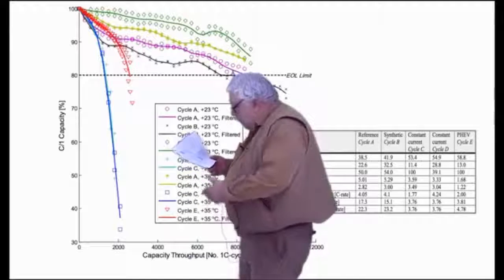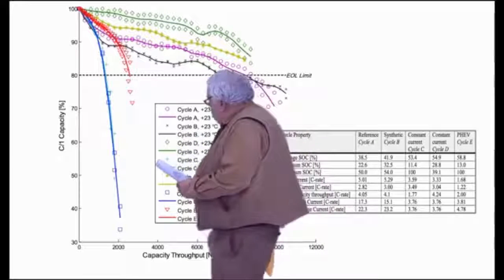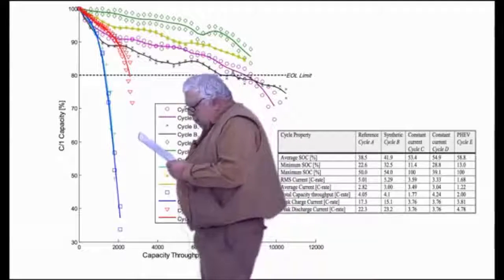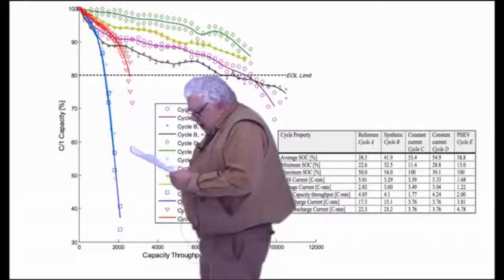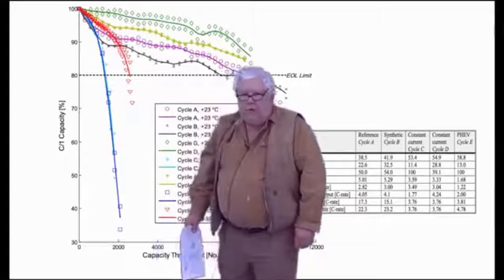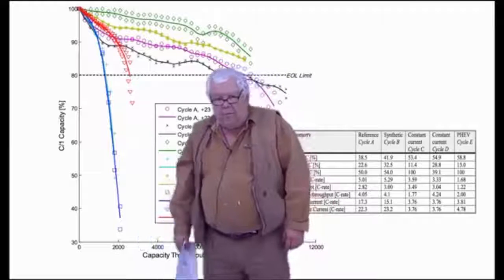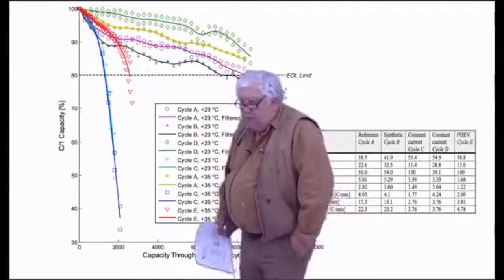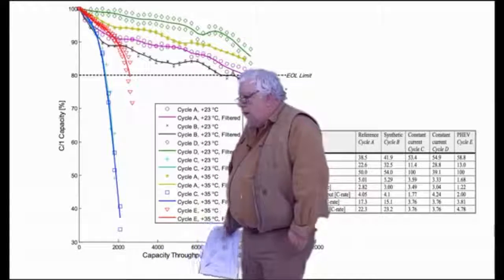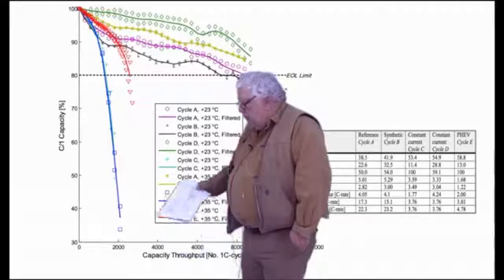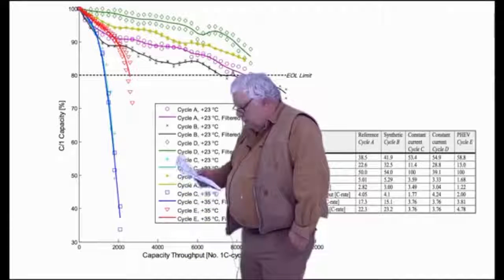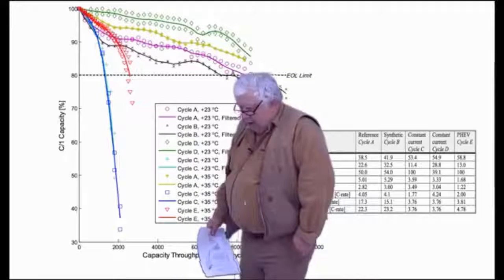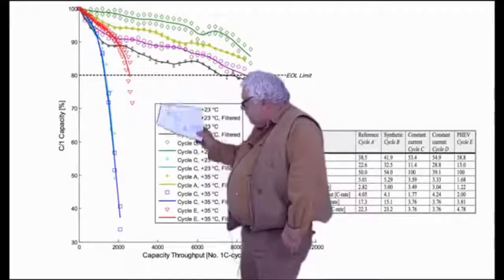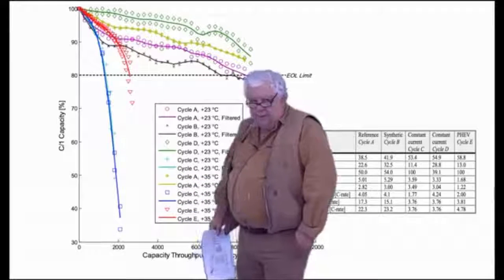But as you can see, the two C cycles both reach 80% of capacity right about 2,000 cycles. And these are indeed LiFePO4 cells. They're not the ones we use. They're not A123 and they're not CALBs, but very similar cells in all respect. And so when we say you get 2,000 cycles, this is the testing that does this.